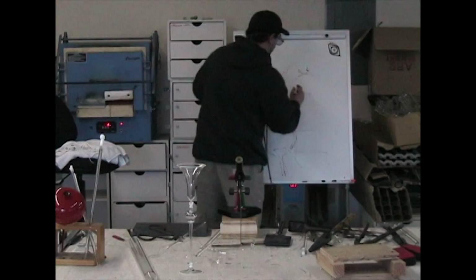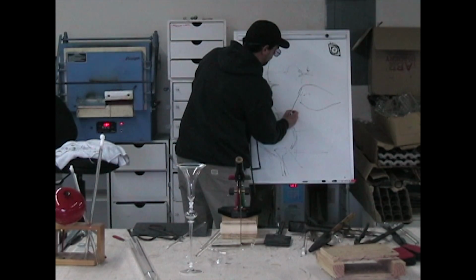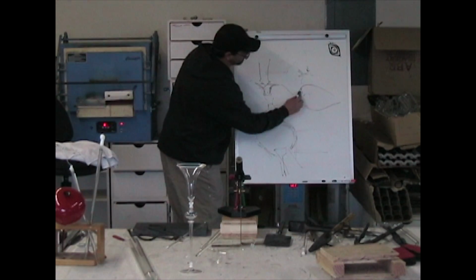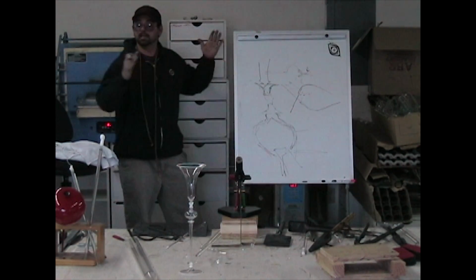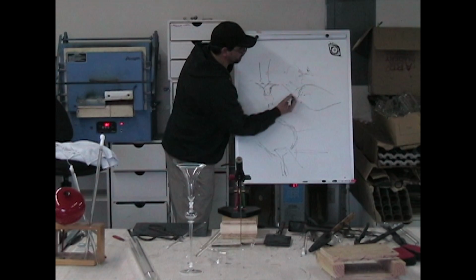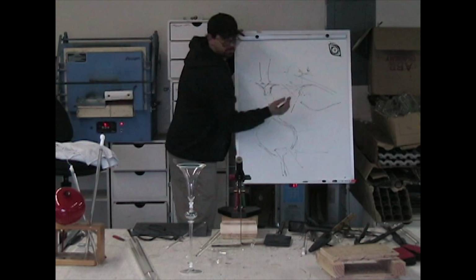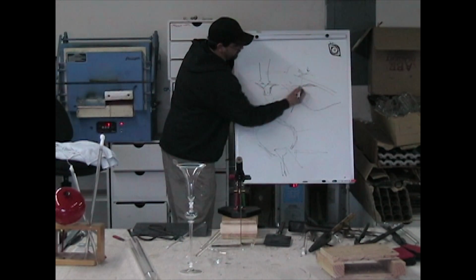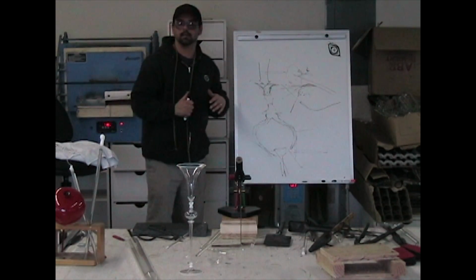Once again, the most important thing, and I'll probably say it a billion times, the most important thing when using the jacks is opening up at the angle of the shoulder. Since it is a lifting out motion, that motion is what's going to get you the maximum results, the lifting out at this angle. And then as that opens up a little bit, then maybe you go in a little bit further. And then it opens up a little bit more so you can go in a little bit further. Or then use the jacks on the outside, or the pucellas, and push this little hump in a little bit. So then you can go in and lift out a little bit more. I mean, you can walk that line on the outside of the glass and on the inside of the glass.